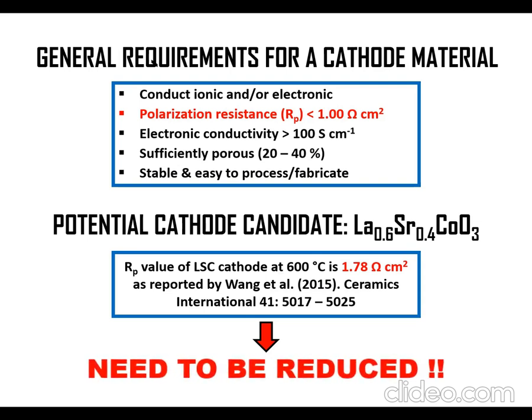Here are the general requirements for a cathode material to be used in PCFC or SOFC application. The main requirement is that the value of RP should be below 1 ohm centimeter square. One of the potential cathode candidates for PCFC application is lanthanum strontium cobalt oxide material. Based on previous research done by Wang et al., the value of RP is 1.78 ohm centimeter square. This value is beyond the targeted value. Therefore, the value needs to be reduced.